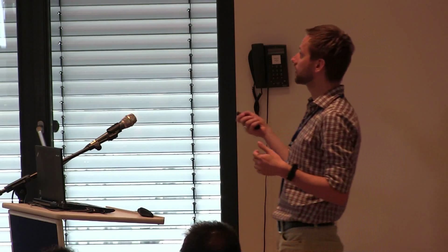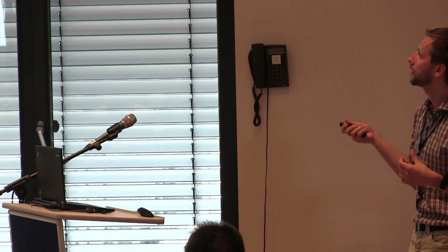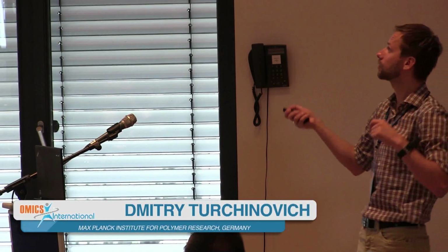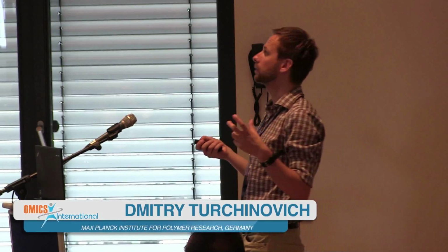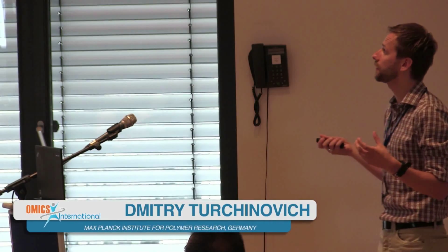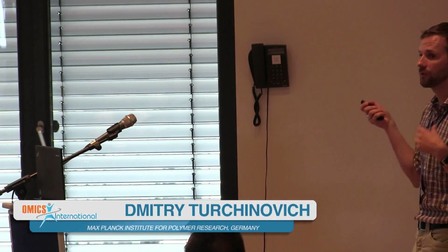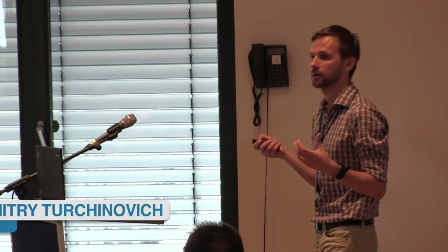And initially it's those ultra-fast microscopic currents that keep this energy, but because of this linear dispersion, the electron-electron interaction is very efficient. Actually, the electron-electron scattering is automatic because the energy momentum in linear bands is always conserved. So any two electrons can do this without the presence of the third particle. So this is very efficient, also very fast, and that leads to very quick thermalization, equipartition of this extra energy among the whole electron population of graphene. And this happens faster than 30 femtoseconds.